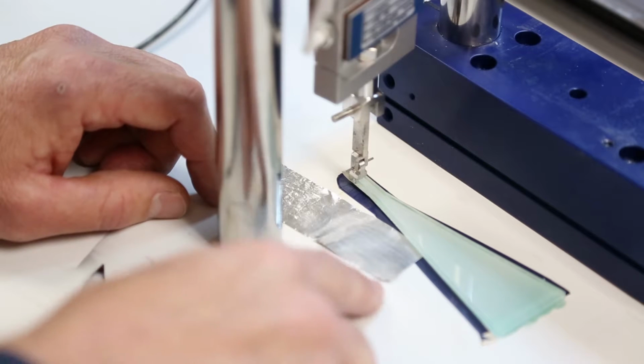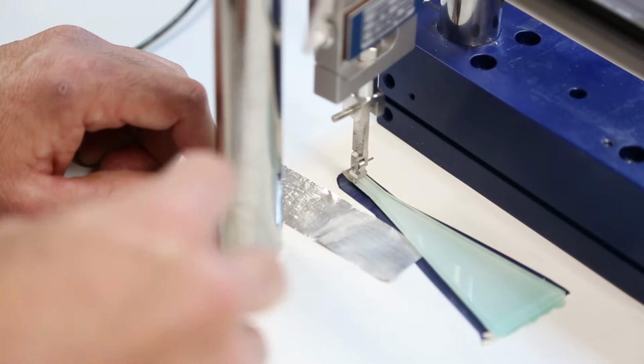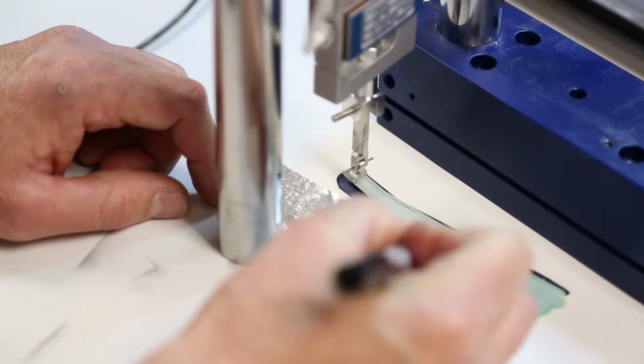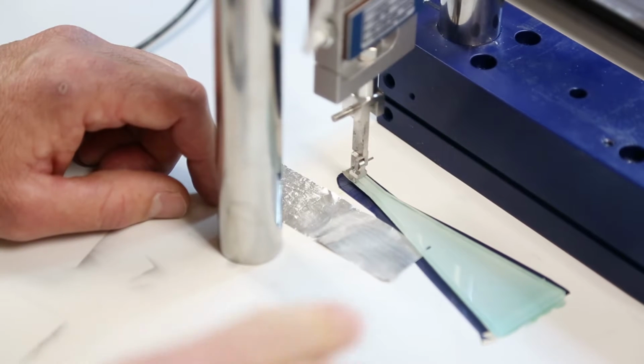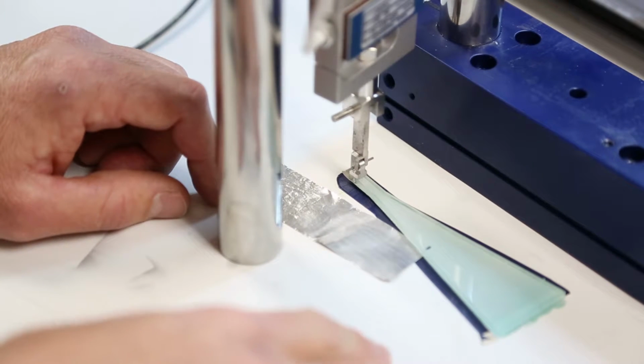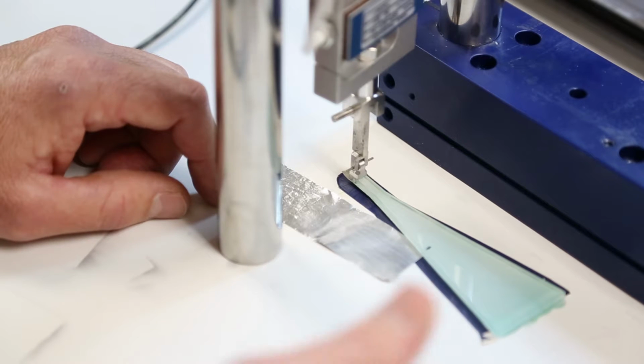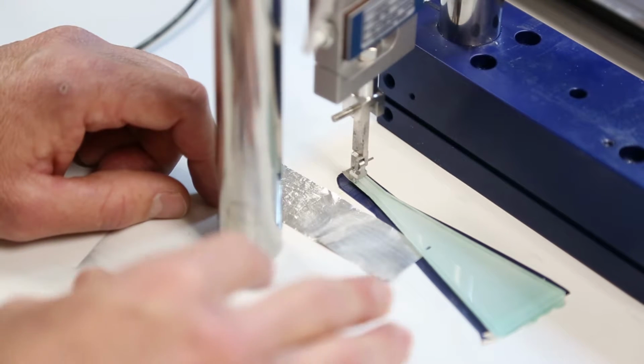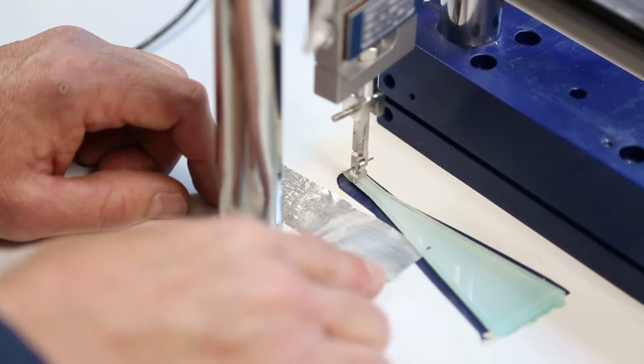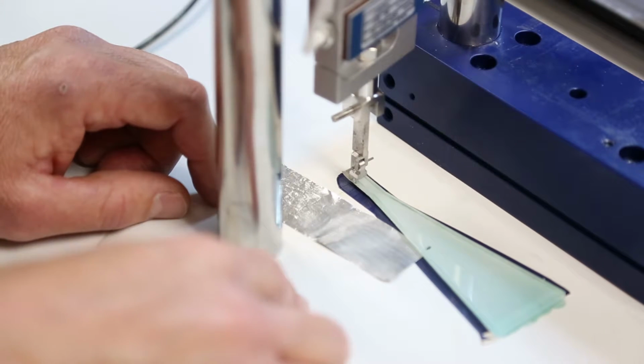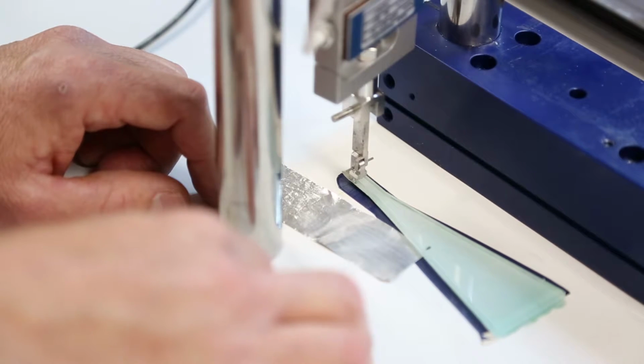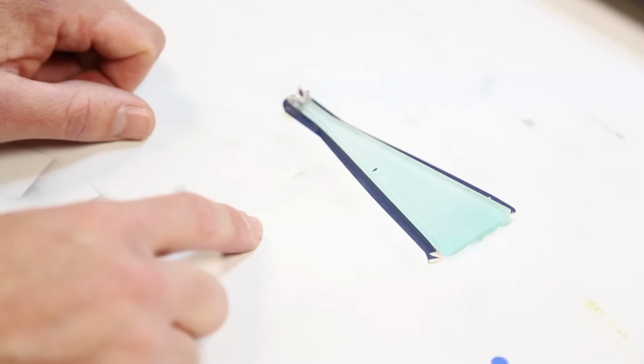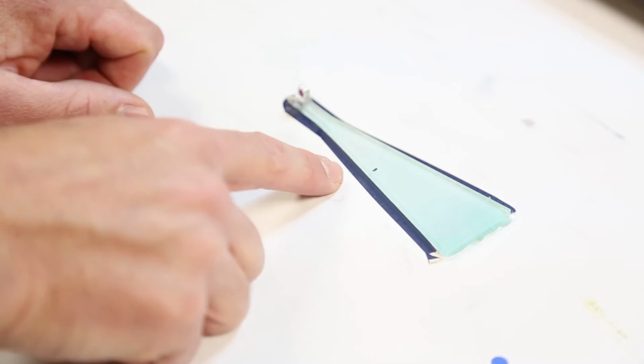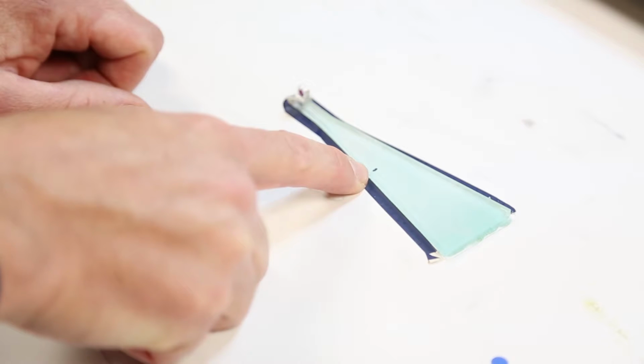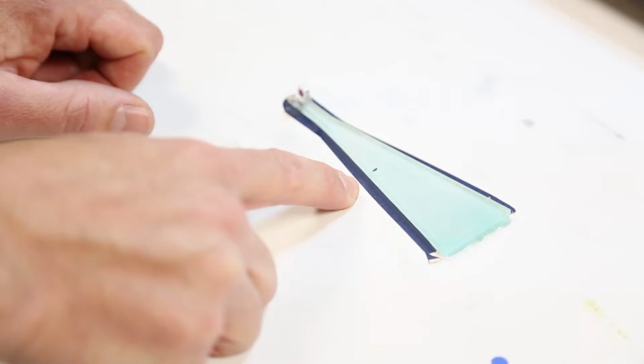When I'm happy with how far it's gotten, I'll make a quick mark on the sample to where I think the debond is and stop the measurement. When I stop the measurement, I'll also unload the sample. I'll do this so the debond doesn't have a chance to run any more before I determine what that final crack length is. So we've concluded our measurement, and with the aid of the foil, I've made a small mark on our beam in the approximate area to which I think the debond has run.